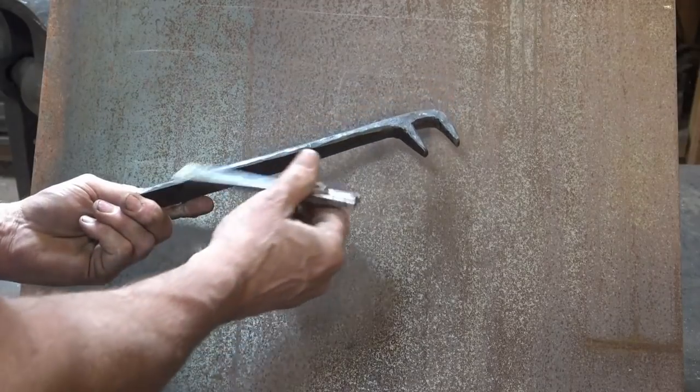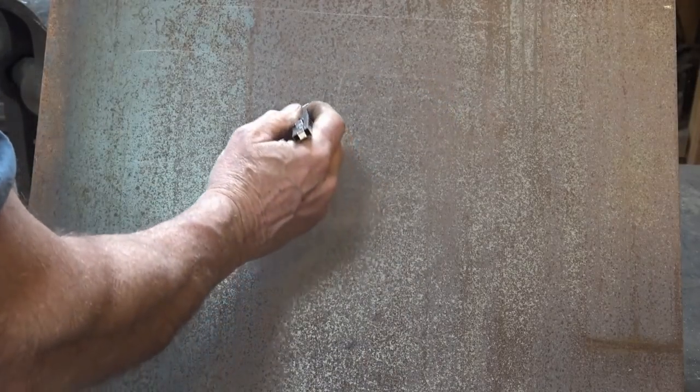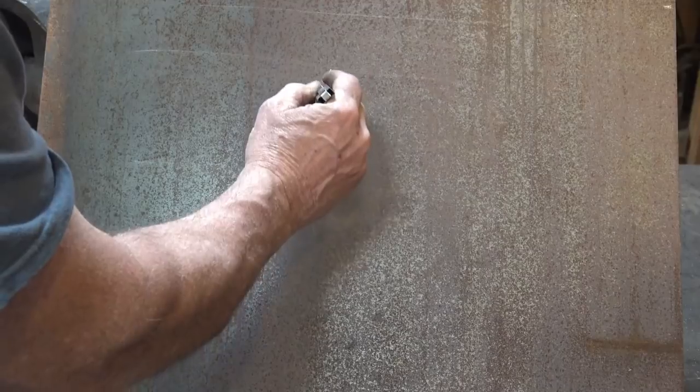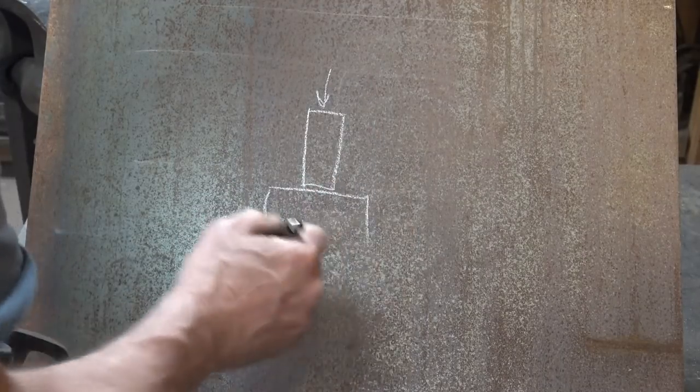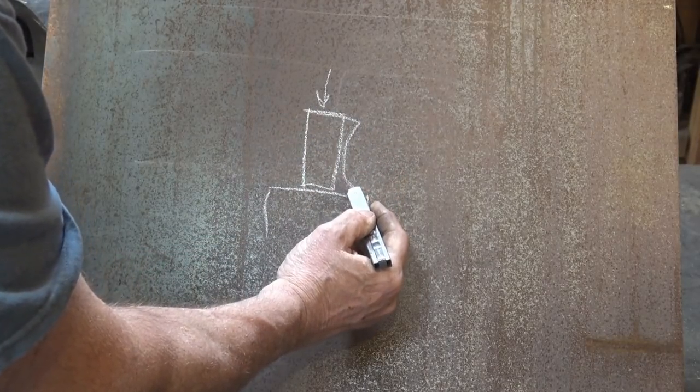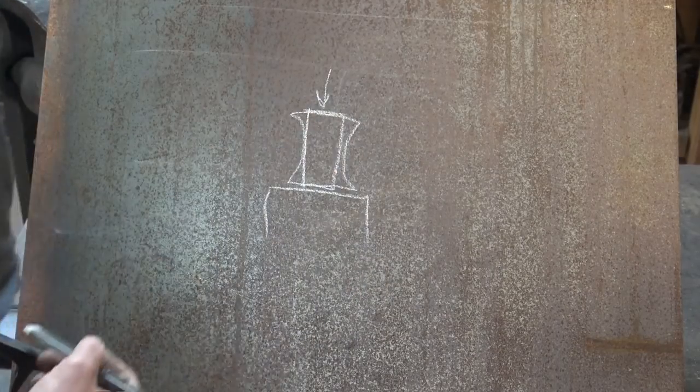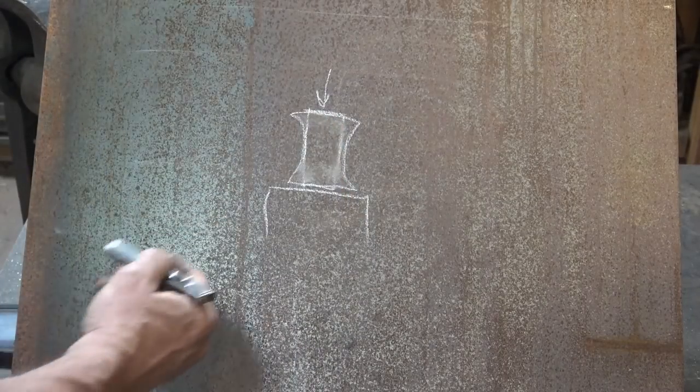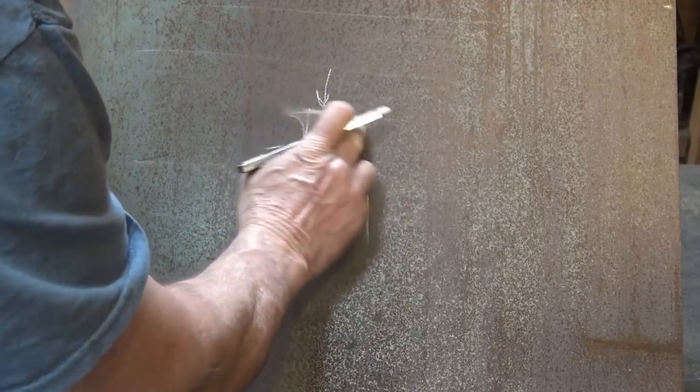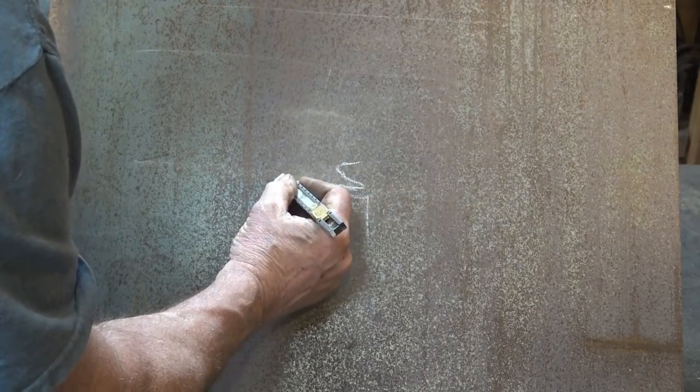The other day when we made this bending fork, I talked about cold shuts here. That's because I was taking a piece of bar that was much taller than it was wide, and I was working it this way between hammer and anvil. What happens then is it starts to spread out up here, but it has a skinny waist. So you end up with something kind of hourglassy like that, or mushroom. This is what happens to your hammers and your chisels as you pound on them all the time.